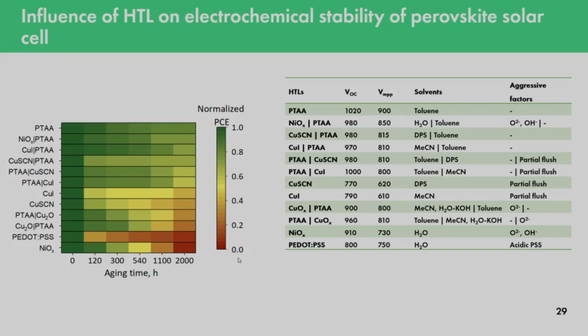And according to this table, which represents the rating of perovskite solar cells with the various hole transport materials, the bottom of the rating belongs to materials which contain aggressive factors like PEDOT:PSS, which includes acidic polystyrene sulfonic acid, nickel oxide, which is first of all water processed, and then it can also include OH minus in its structure, copper oxide, and then go copper salts, which can probably be partially flushed by perovskite solvents. It's not confirmed, but still it's sometimes observed in the literature.